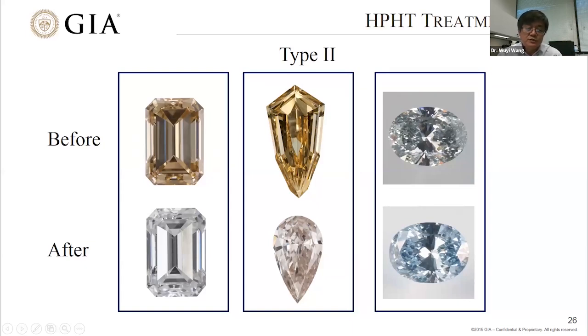So here we just want to show that HPHT treatment is very effective in changing the color of type 2 diamond. And of course, similar to irradiation treatment, the final result will heavily rely upon the starting material chemistry. It is almost impossible to turn a gray diamond pink after HPHT, or for a brown diamond, after the treatment, to turn blue. The final color heavily relies upon the starting material chemistry.